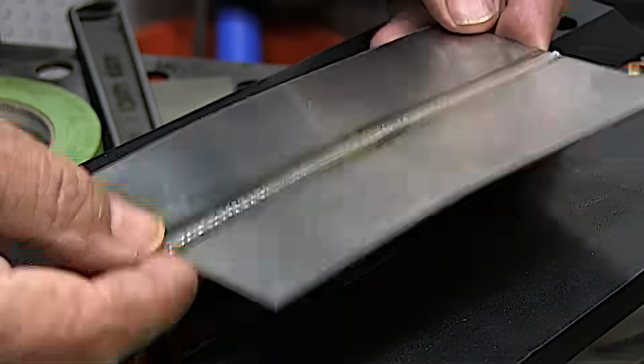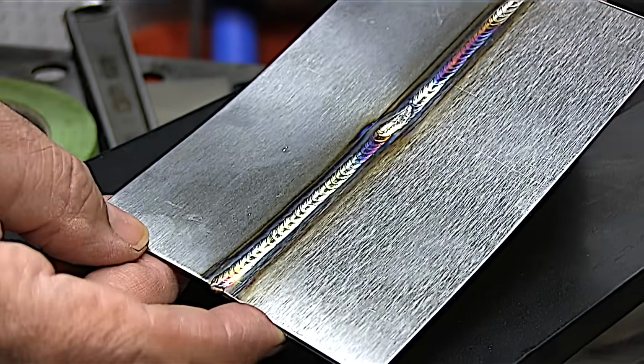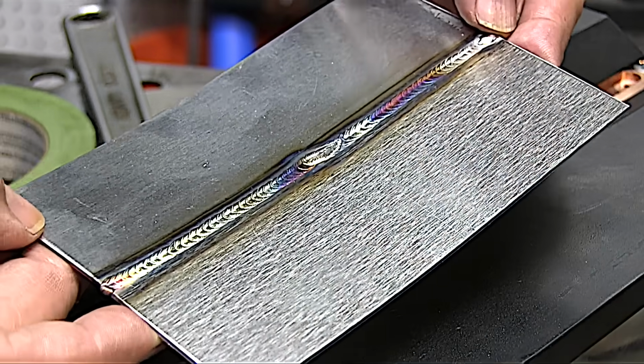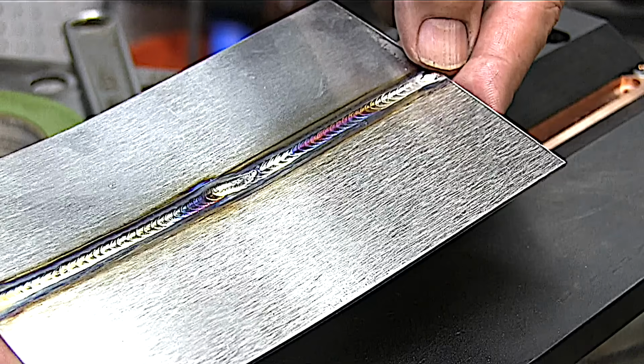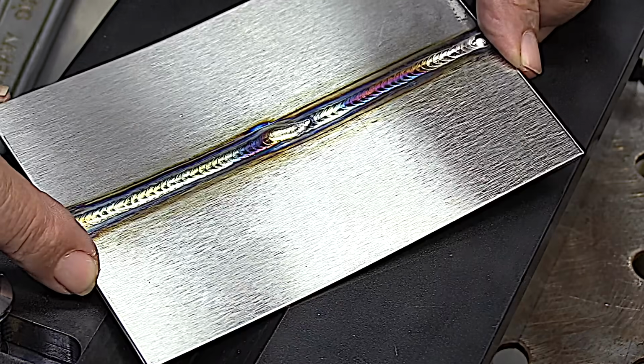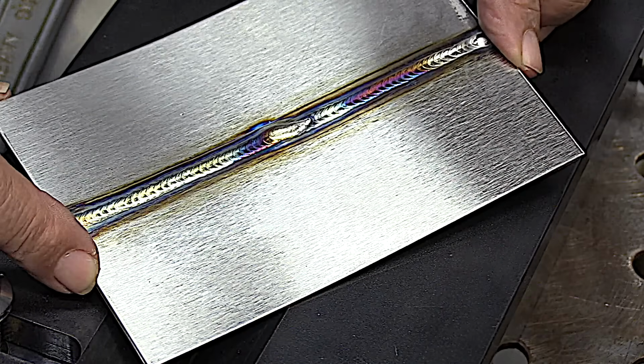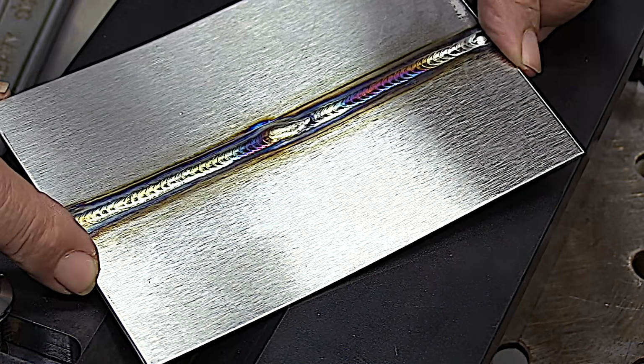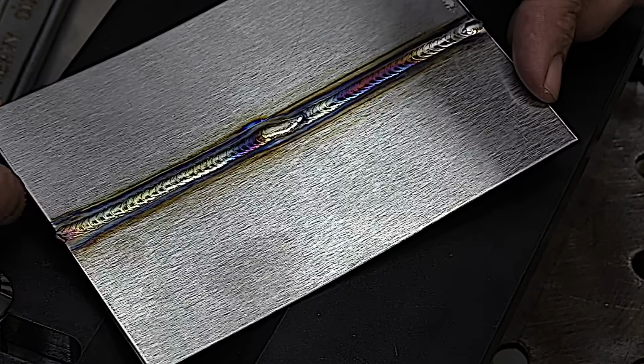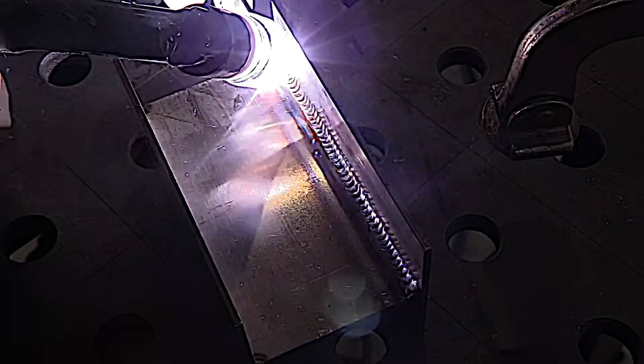With this test piece being in a purge fixture, it got nice and silver on the back side, with a little bit of colors on the front side, which might look nice, but in some industries that would need to be removed. While those colors might look pretty, they are a layer of oxidation that is more prone to corrosion than bare stainless. Let's take a look at a T-joint now.